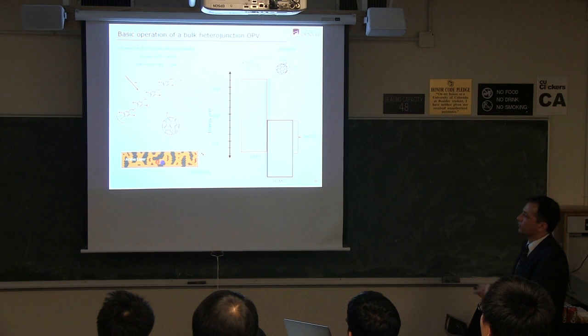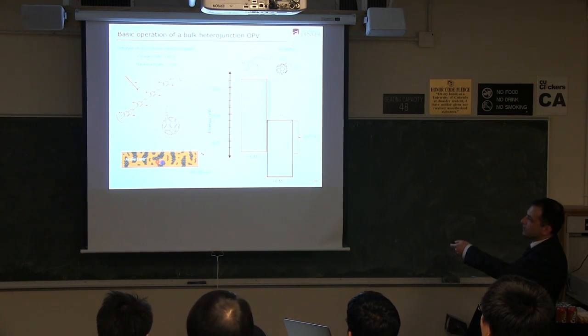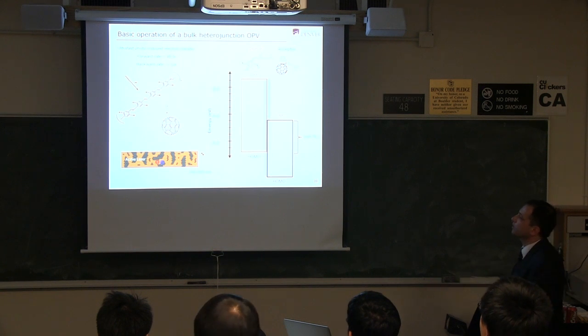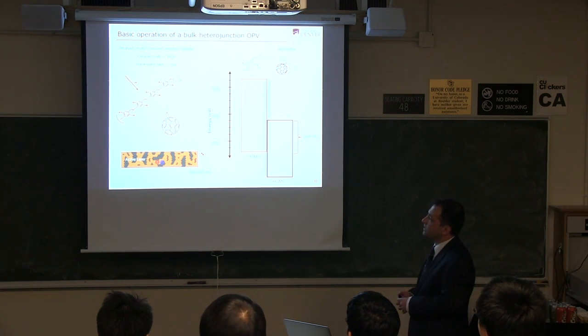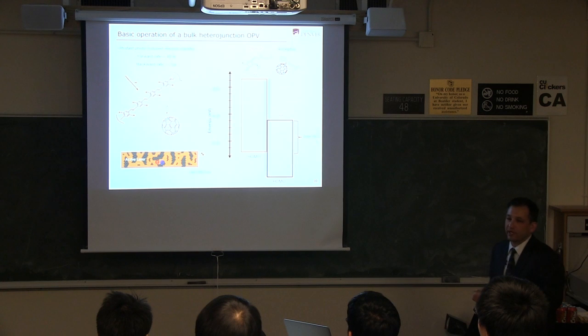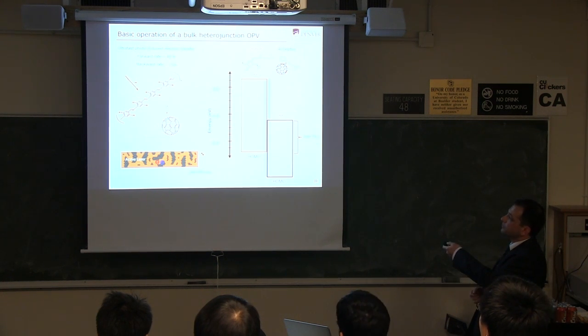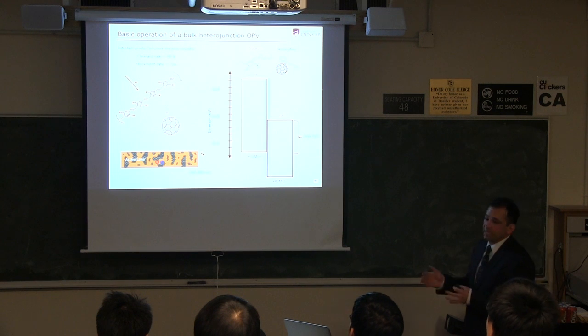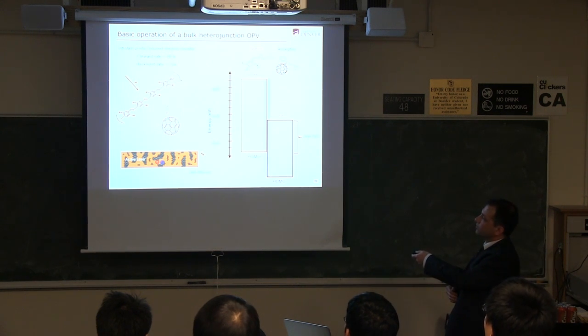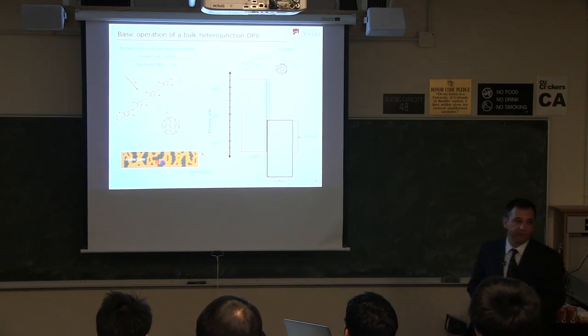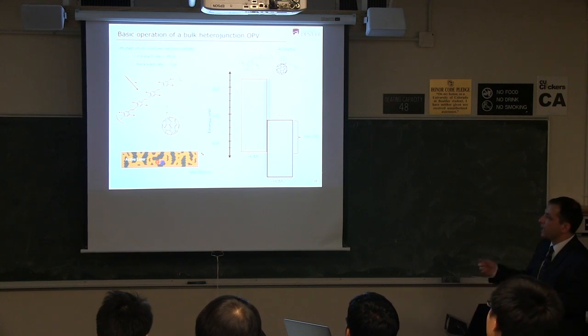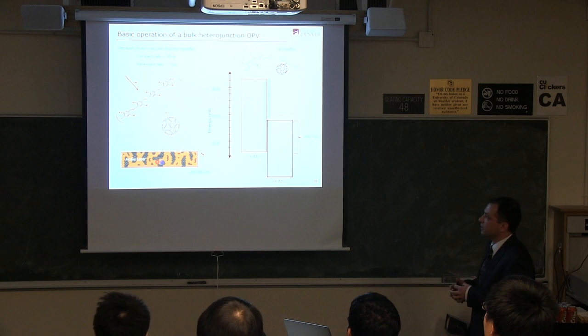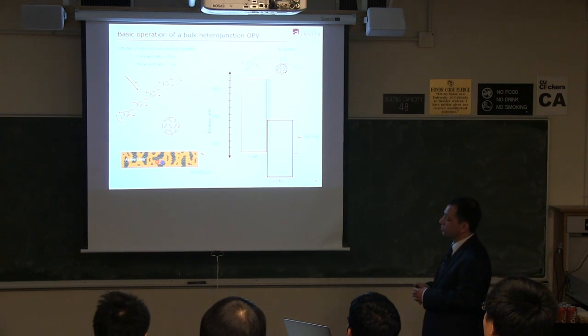ultra-fast electron transfer separating the exciton into an electron on the C60, leaving a positive charge, the hole, on the polymer. The important thing is that that charge-separated state lives very long, and its lifetime at room temperature is something like a microsecond. So you have this big asymmetry between the forward transfer rate, which is extremely fast at 50 femtoseconds, 45 femtoseconds, and the backward rate. So that's that asymmetry that allows us to extract charges out of the device and make a functioning solar cell.